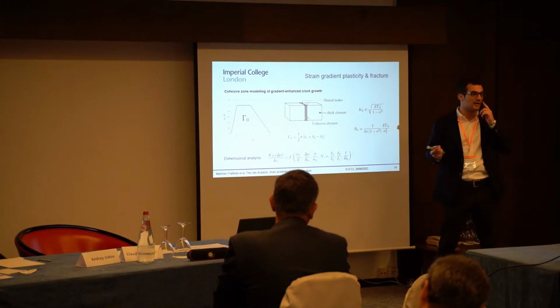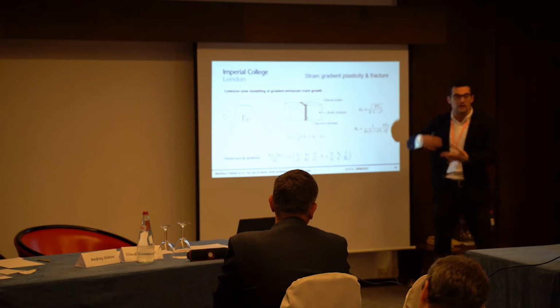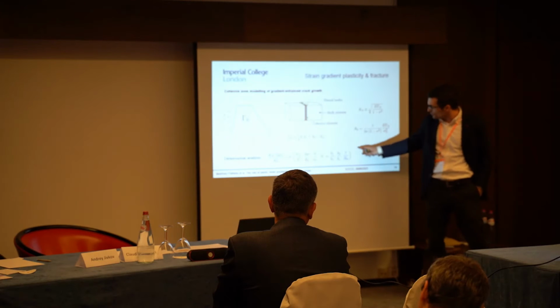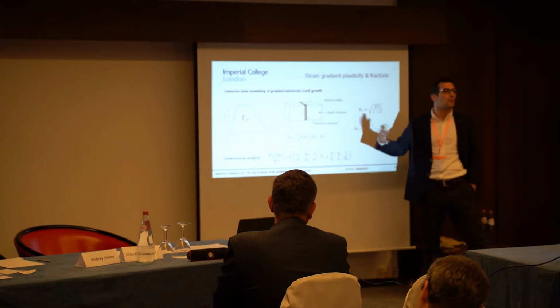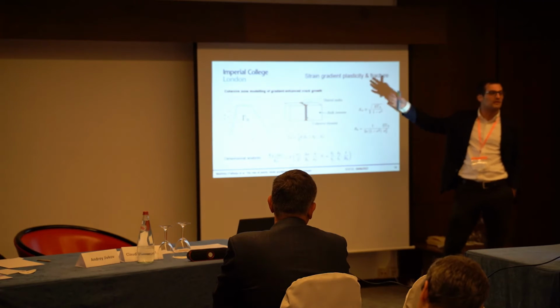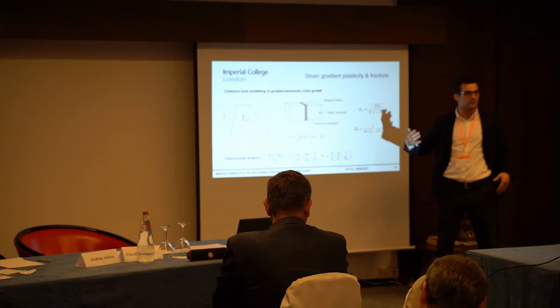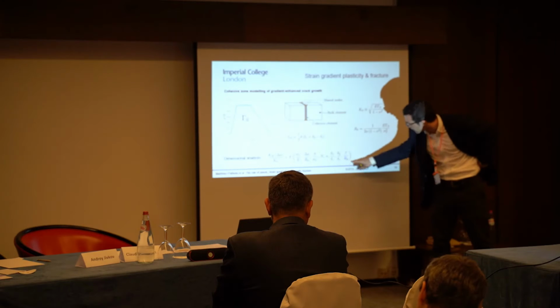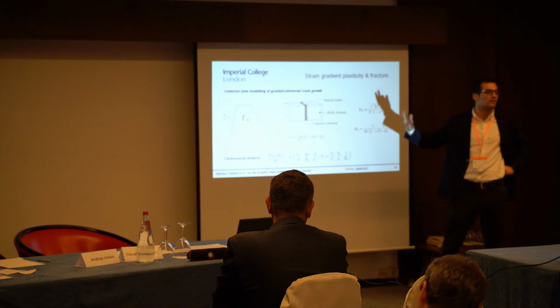So if you do a dimensional analysis, then you will see that your crack growth resistance curves will depend on a number of non-dimensional sets, and this one in blue is the most relevant one, which is the one that doesn't show up in conventional plasticity. You have a length scale, that material length scale that characterizes the ability of your material to harden due to GNDs, and then this R0, which is a measure of the size of the fracture process zone or the plastic zone.